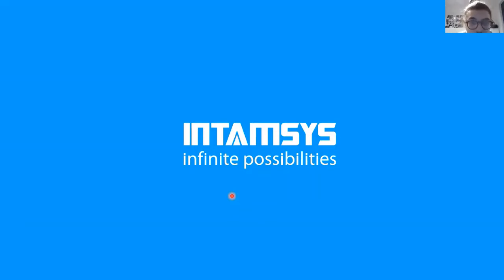What I would like to do is to answer the last questions. Do you have an idea about layer lines in PEEK? Do they have something to do with amorphous versus semi-crystalline printing, causing color difference? One point, and this especially happens with semi-crystalline printing, is that different layers have different shrinkages, and this has a big influence on the surface. When your geometry changes from slice to slice, from layer to layer, you have a different crystallinity in each layer, and a different grade of crystallinity gives you a different shrinkage. This provokes a worse surface and also makes layer lines more visible. So definitely printing amorphous and then annealing afterwards gives you better surface results than trying to print in a semi-crystalline state.